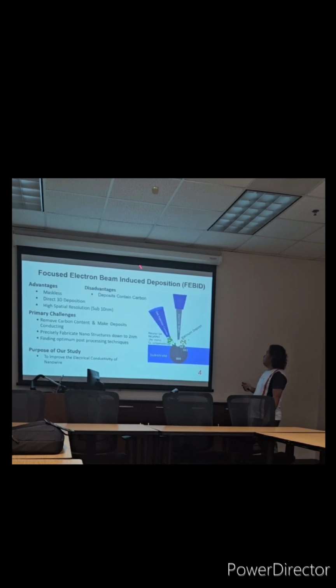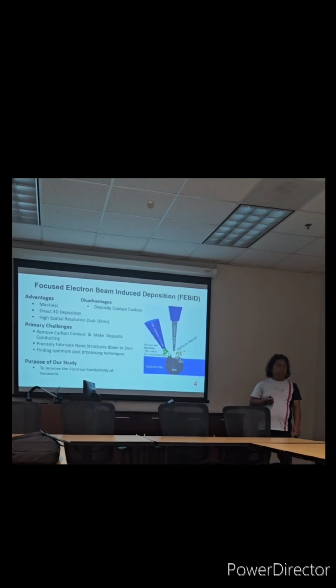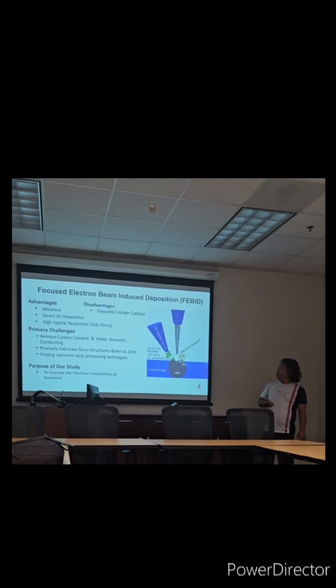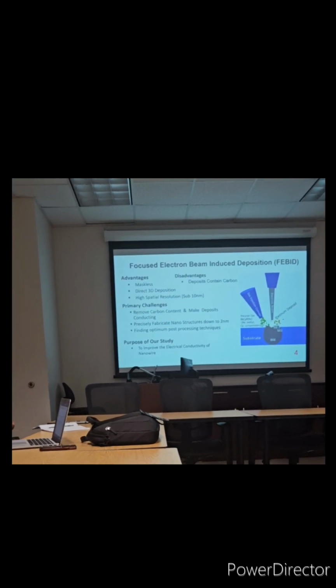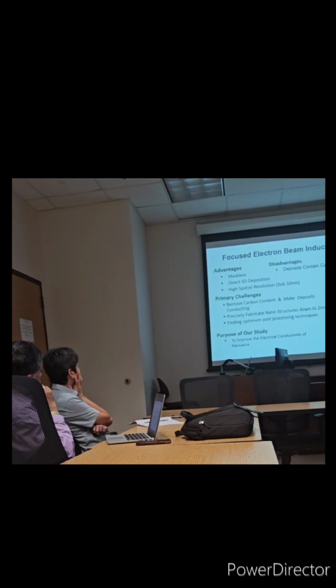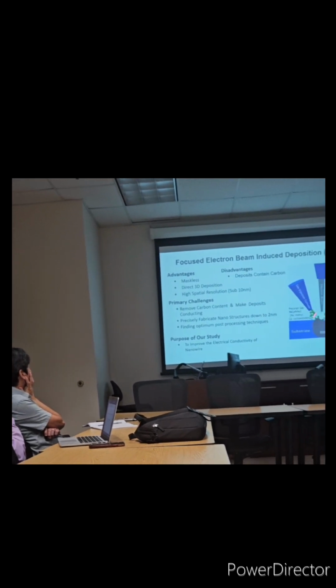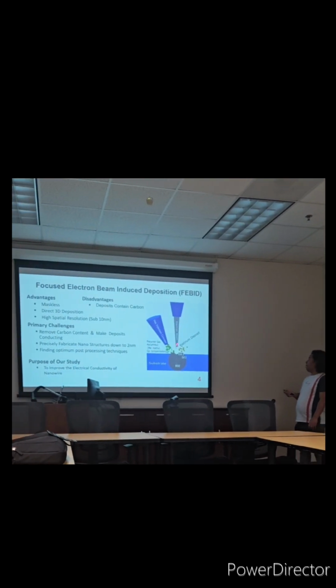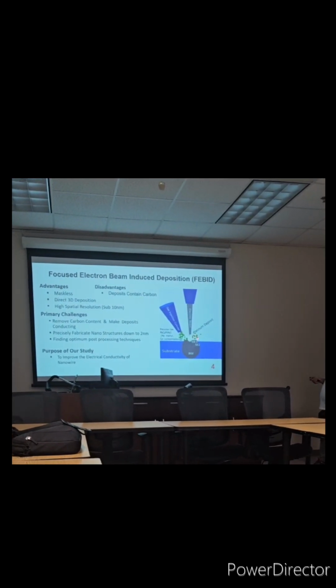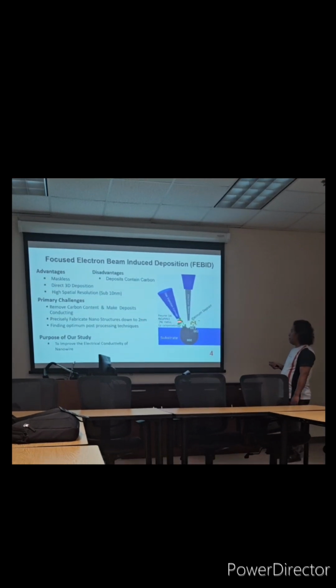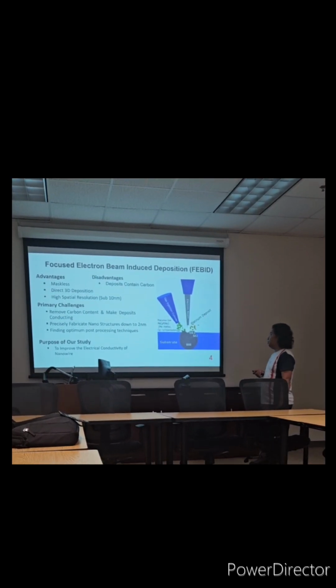Focused electron beam-induced deposition is a process of dissociating or decomposing incoming precursor gas that leaves non-volatile fragments or substances deposited onto a substrate. Here in the picture, it shows that an incoming electron beam dissociates the precursor gas. In our case, we use trimethyl cyclopentadienyl platinum. Platinum gets deposited and the volatile fragments such as carbon dioxide or water are removed from the chamber.